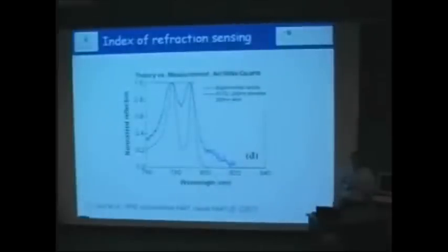Some examples of measurements we did in comparing, talking about designing something and then going to the lab and fabricating. Many times when you try to fabricate a device, it's not always the best. So this is some of our efforts from 2 years ago, where you could see the simulated resonances. One is TE-like, one is TM-like, and you can see that the resonances are not exactly matching. The location is matched, but the width is not as good. Usually this is due to disorders in the fabrication.